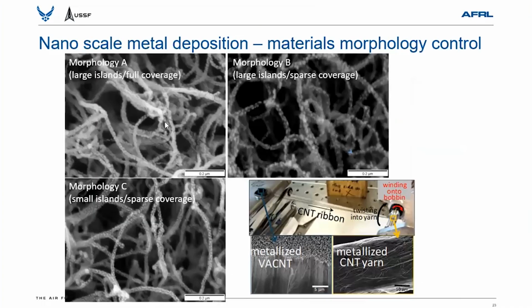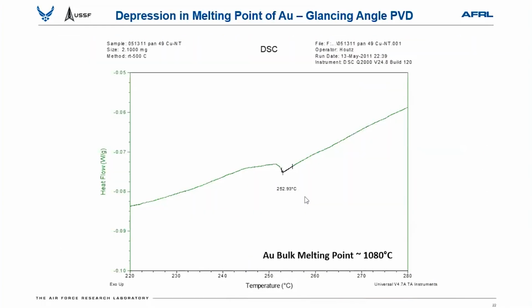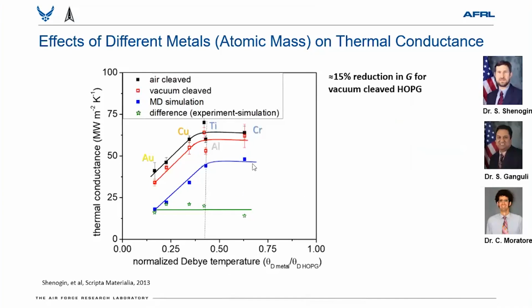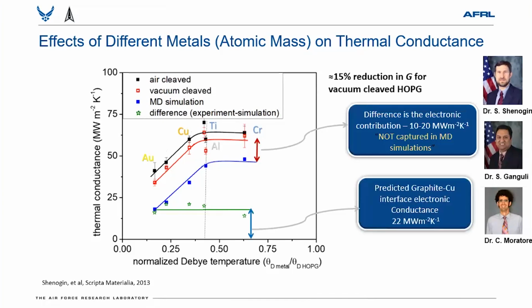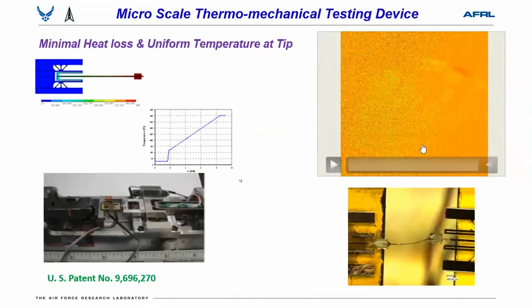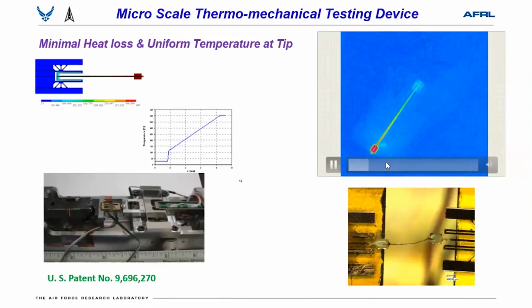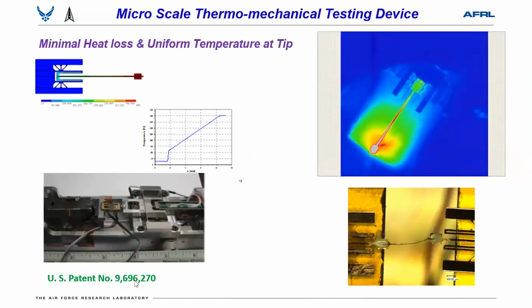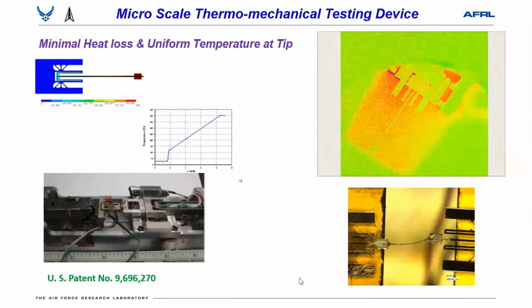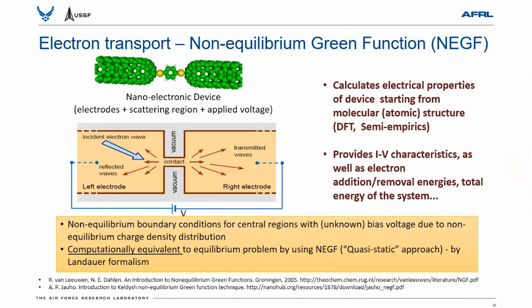So with this, we decorated nanotubes with gold nanoparticles of different sizes, and also with other metals. And we found, as we predicted computationally, chromium, titanium, and copper are much better than gold. And that is validated experimentally. We measured those properties, and those measurements were done on a micro-scale testing device we have developed, and that is patented in our laboratory.